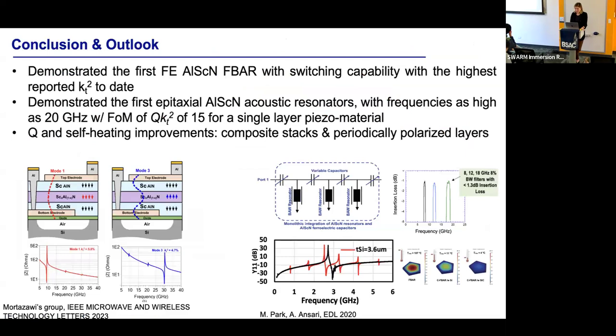Now, let me conclude this section. I showed some ferroelectric aluminum scandium nitrides, which were the first of their kind with the highest KT squared to date, and showed you high figure of merit FBARs. However, as we saw, the Q can still be improved. It's not close to the material limit. It can be a lot higher.